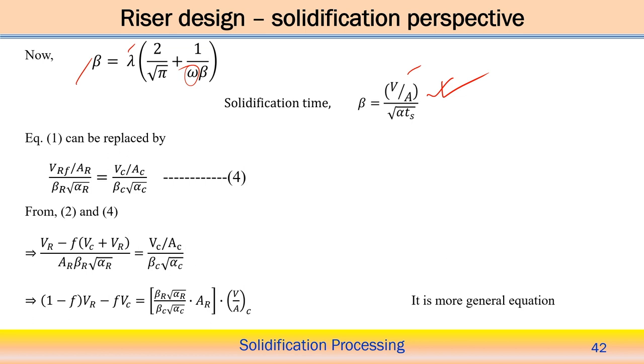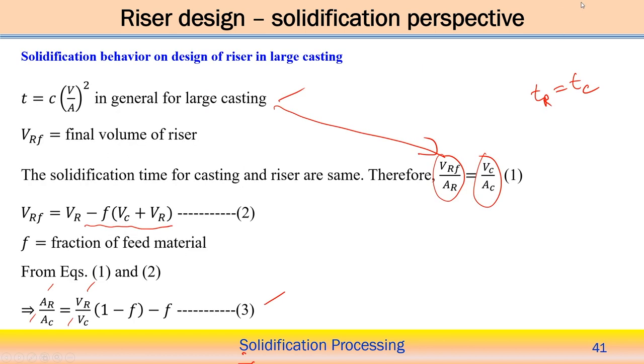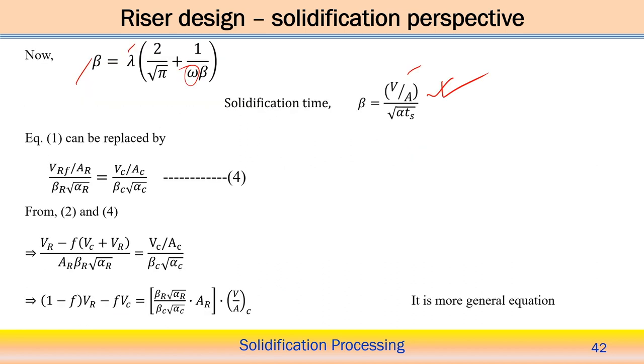Now equation 1 can be replaced like that. Equation 1 says the volume by area ratio should remain constant, because the solidification time is the same. So equation 1 indicates that the volume by area for the casting and the riser is the same in this case. Now equation 1 can be replaced by considering this effect. So here beta equals volume by area by beta into the square root of alpha TS, because this equation can be modified: the square root of TS can be written as V by area by the square root of alpha into beta. So that gives the square root of TS, the solidification time.